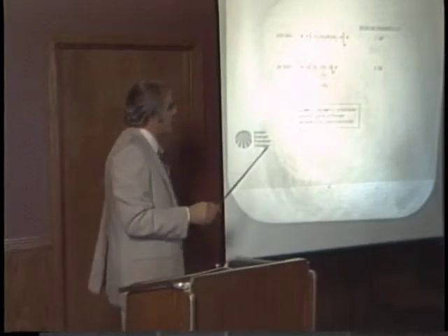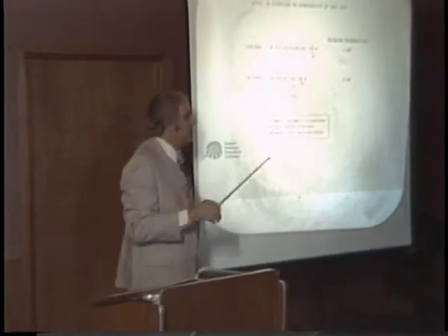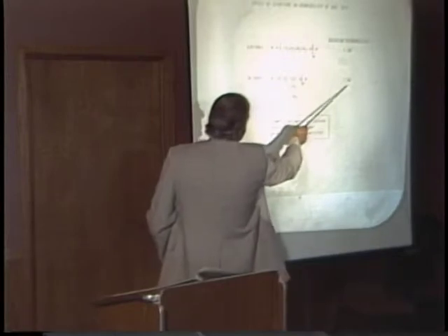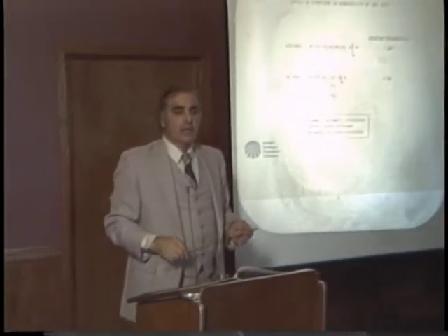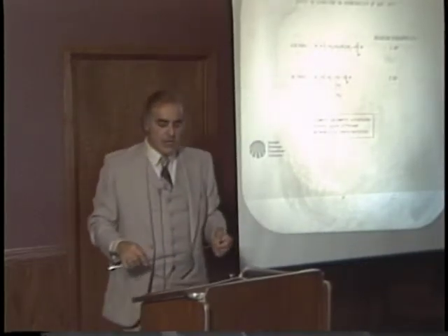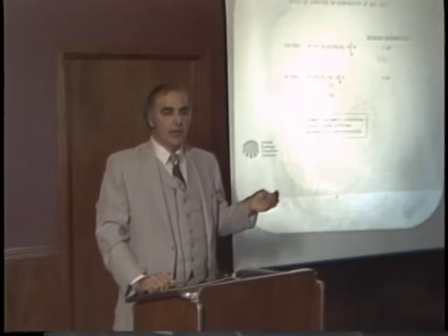It cannot crystallize readily. So in this, we cross-link the systems to the same cross-link density, try to keep everything constant, and we measure the relative permeabilities, and we find that this material has a permeability coefficient something around 3.5 times greater than this one over here. So we have to deduce that there is a definite effect of the structure of material and not just the polarity effect. So these are isomers that show differences.